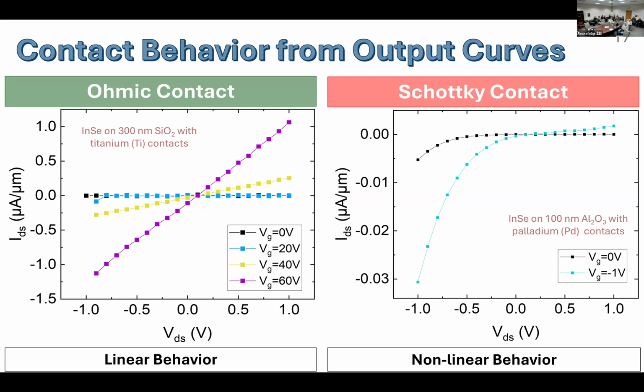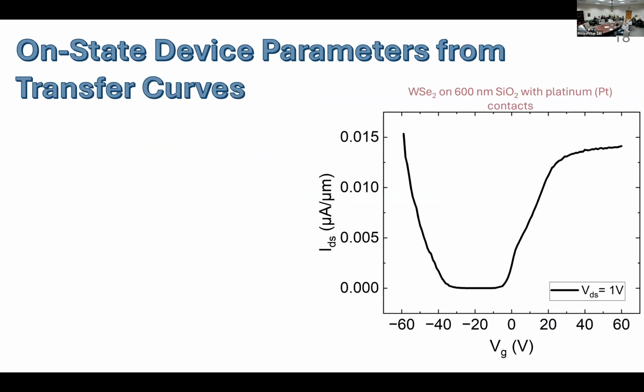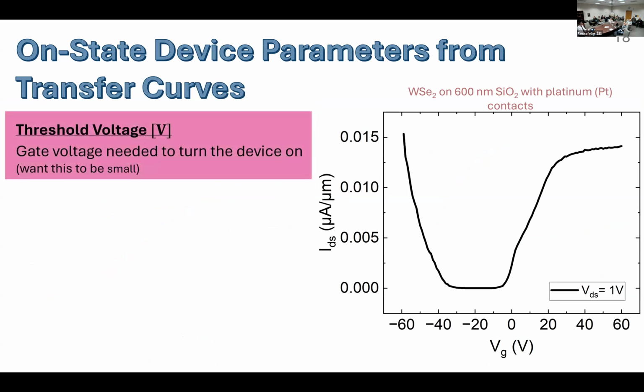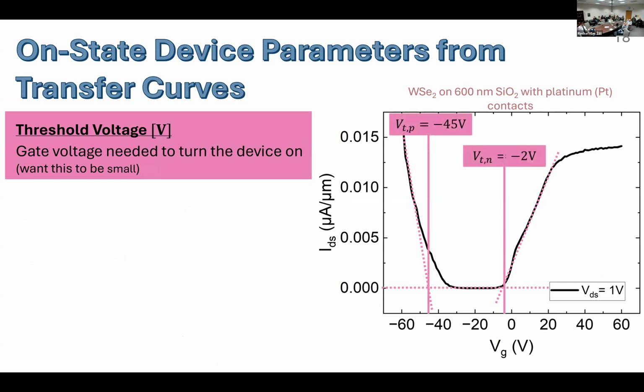So contact behaviors from output curves, and we can get a sense of how our device responds to the application of a gate voltage by looking at the transfer curves. So again, this measurement looks at how the source drain current changes as a function of the gate voltage. From these kinds of curves, we can extrapolate important device parameters such as the threshold voltage. To do this, we simply look at the linear regime of our graphs, we draw a line and see where that intersects the zero axis. And then that will give us our threshold voltage. This is a measure of how much gate voltage is needed to turn the device on.